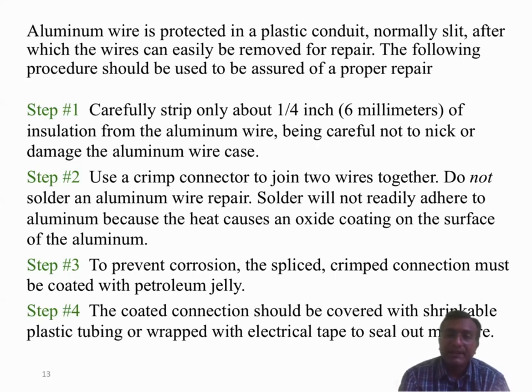Solder will not readily adhere to the aluminum because heat causes an oxide coating on the surface of aluminum. To prevent corrosion, the spliced crimp connection must be coated with petroleum jelly. The coated connection should be covered with shrinkable plastic tubing or wrapped with electrical tape to seal out more moisture.